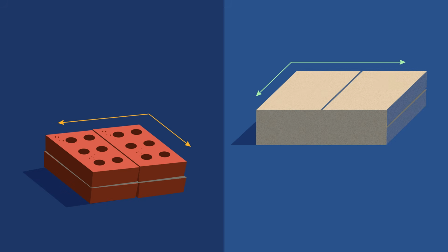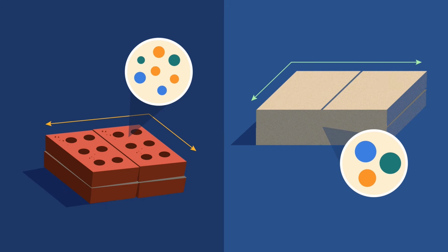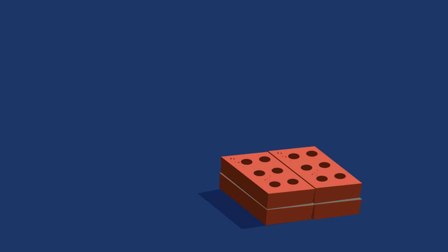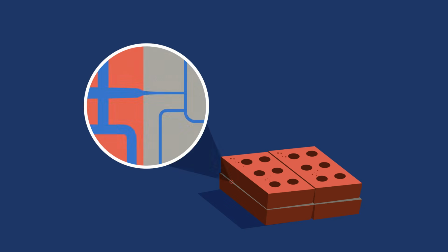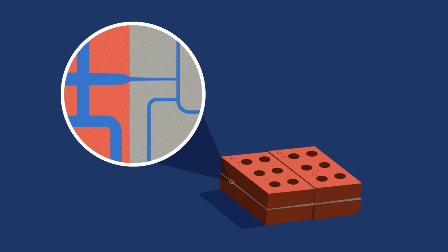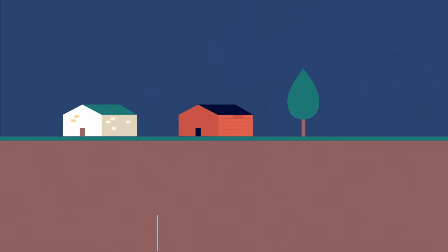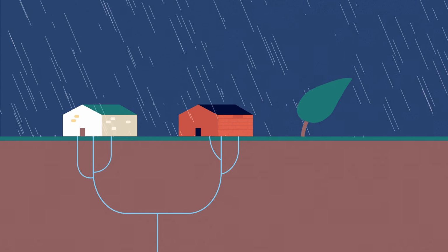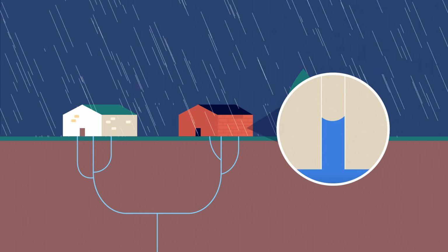The relative dimensions and properties of these components play an important role, and should be considered when conservation interventions are carried out. For example, the difference in pore size between the mortar and masonry elements would determine the direction of fluid flow, while sorptivities would determine the rate at which groundwater or wind-driven rain would be absorbed by either of these materials.